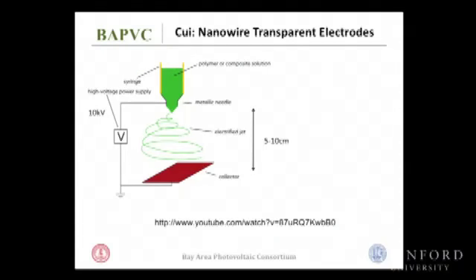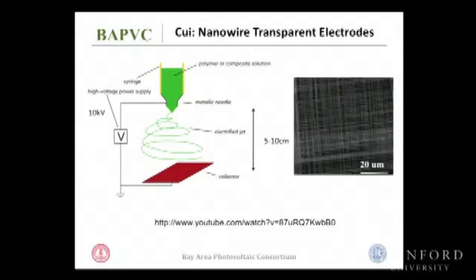So I have another project going in the group related to a consortium. We have also been trying to develop a transparent conducting electrode, which can be combined with the solar cells. There's a process called electrospinning. This is a polymer and a needle, and when you apply a voltage, you charge up this polymer, and the strong electric field will extrude out this fiber very, very fast. When I looked at this idea several years ago, I said this might be possible for us to make a nanowire transparent electrode like this, with a metallic mesh covering large areas. And if you can make metallic nanowires this way, it's possible to generate a high performance transparent conducting electrode.